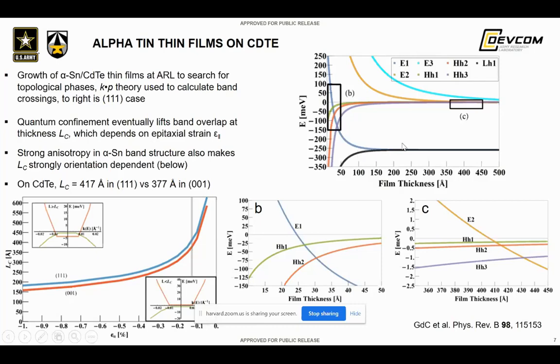But the important thing to point out is that at some point you go from a 3D topological insulator when you have these band hybridizations. These two plots are the symmetric and anti-symmetric hybridizations of a topological surface state. When it starts to gap, you essentially lose your three-dimensional topological insulator characteristics, and the material becomes more like a 3D trivial material, or 2D topological insulator, or quasi 3D trivial material. And as it goes to smaller thicknesses, you get a 2D insulator, and at some point a 2D trivial insulator.